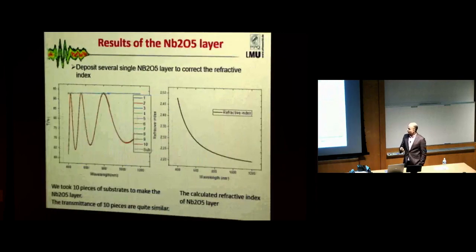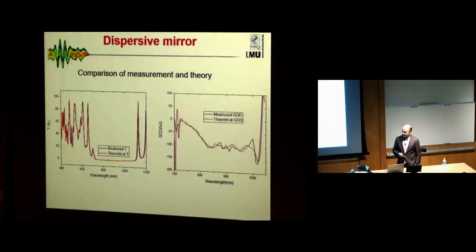To improve this, we run our machines many times with single layers to get the properties of our layers with very good precision. Here is the curve for single layers. By fitting this curve and choosing different dispersion for the refractive index, we can nicely identify the refractive index curve. And by using the new refractive index curve, we can improve our deposition much better, so our measured curve looks much closer to the theoretical curve. Here we have a transmission measurement, and you see that the theoretical and measured curves almost coincide. And this is the group delay dispersion.